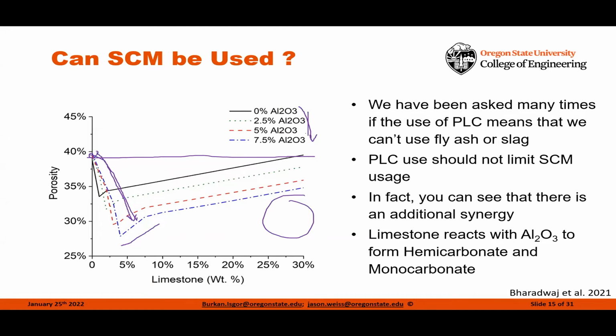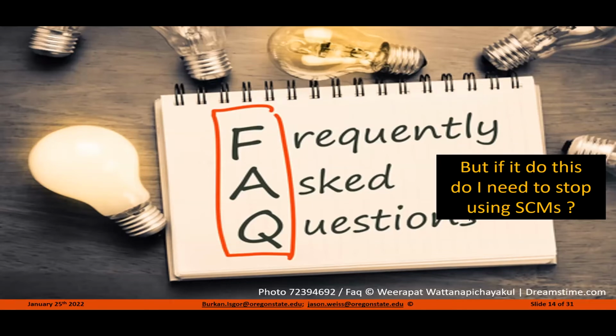So all of a sudden, we're able to start to design the amount of limestone we may want to have in these systems based on some of the other components that are there. So it's actually synergistic and beneficial to be using SCMs with Portland limestone cement, and it shouldn't be something that we're trying to take out of the mixture. So again, just to drive this point home, if you're using a C595 cement or you're using a limestone in the system, it's beneficial to use that with your SCMs, and that's really what we want to be doing as we move this forward.